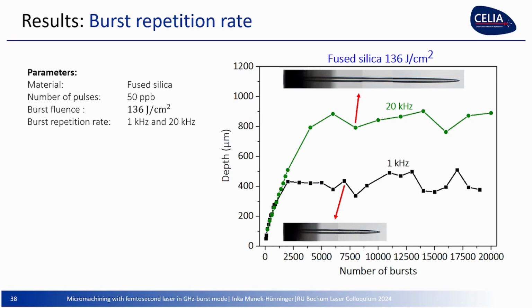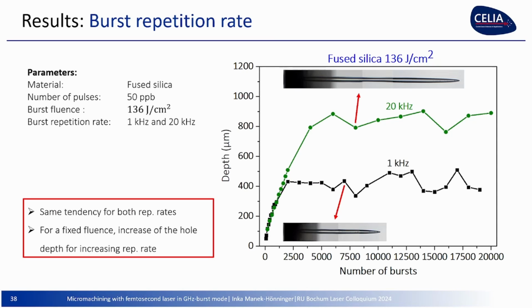So let's have a look on the burst repetition rate. We kept everything constant, 50 pulses per burst, 1 fluence. And when you have a look at 1 kilohertz or at 20 kilohertz in fused silica here, easy to see, the hole is deeper at 20 kilohertz. So for fixed fluence, at a higher rep rate, you can drill deeper.